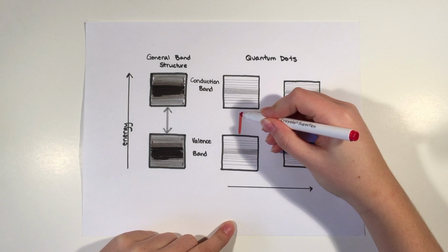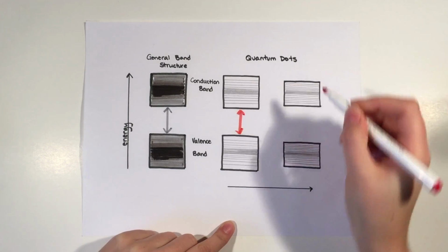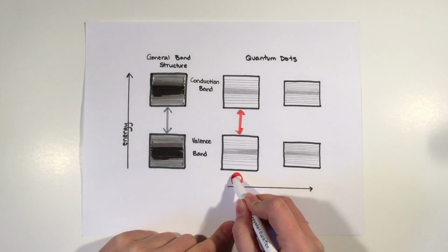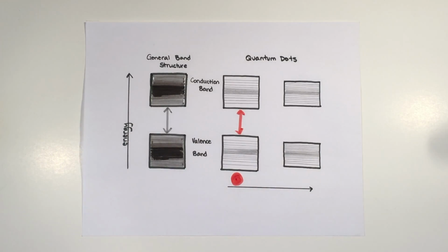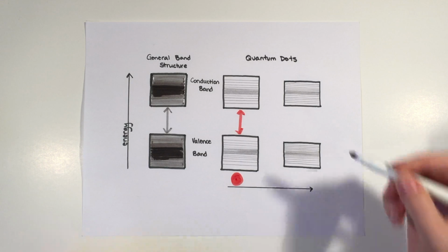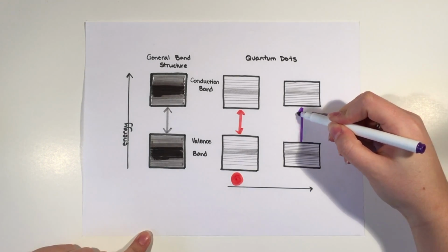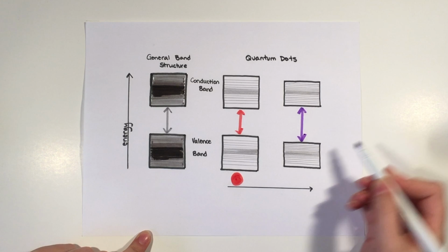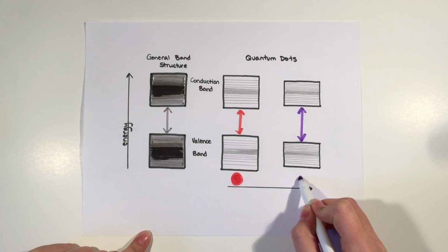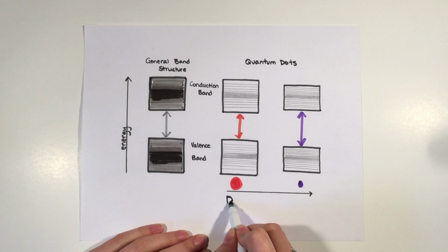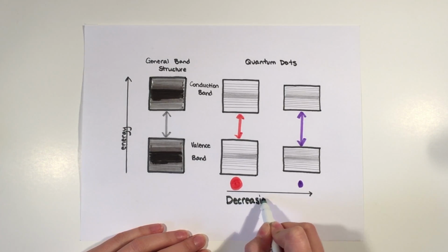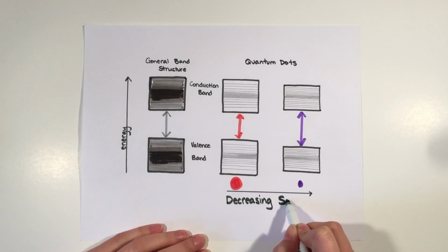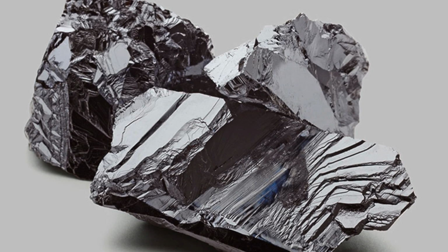Quantum mechanics dictate the behavior of very small particles. At this scale, within molecules, quantum confinement states that the smaller the particle, the larger the gap between the conduction and valence bands, and the higher the energy of the photon emitted. With this material, cadmium telluride, if you were to shine a UV lamp onto a macro-scale piece of cadmium telluride, you would notice that there is no emission of photons that are visible to the human eye because the band gap at this size is very, very small.